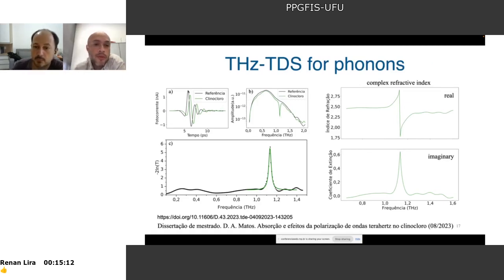So the Fourier transform of the reference is this black line. It shows you all the frequencies contained in the incident pulse. So this pulse has all these frequencies from 0 to 2 terahertz. This is our experimental window. The maximum is more or less like 0.6 terahertz.